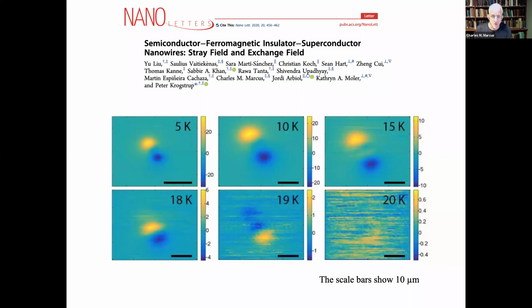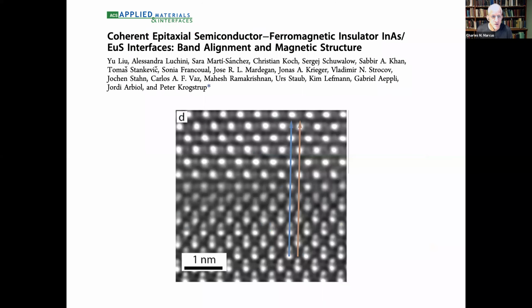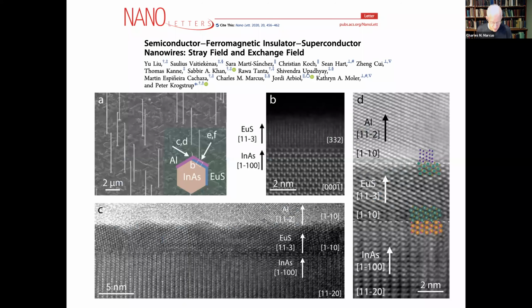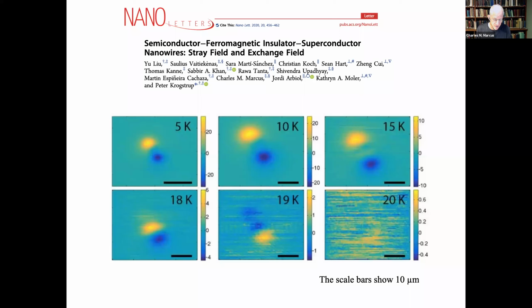The part of this that Kam Moler and her lab were involved in had to do with doing a scanning SQUID measurement. If I go back, I can show you. Oh, I think I chopped it out of this first picture. I'm sorry about that. Kam has a setup that takes a small SQUID loop and at low temperature moves it around over material. This was on an insulating benign substrate, with deposited wires that had the ferromagnetic insulator and the superconductor on the substrate. And Kam can scan the SQUID with micron scale resolution.